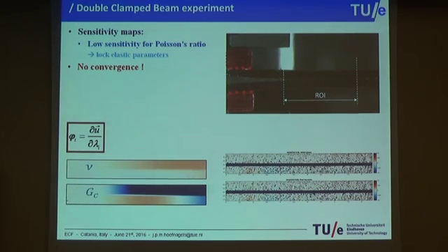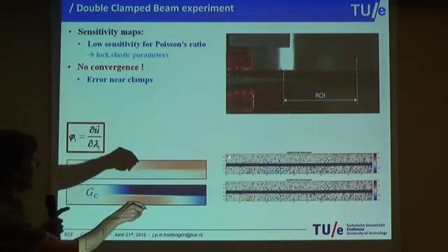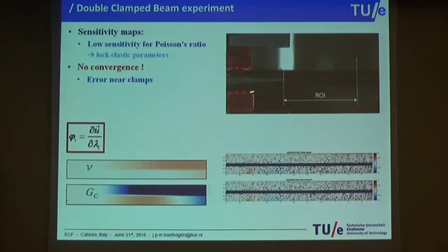So this whole theory sounded very good, and in theory it worked better than finite element updating. In practice it was not working. So what could we do? We went back to virtual experimentation. Before we did that, sorry, we noticed that already here, near these clamps, there were errors. So we're thinking this is not good enough. Maybe there's a glue layer here that's doing something funny, which we're not capturing.